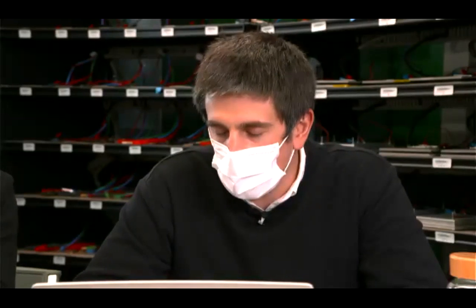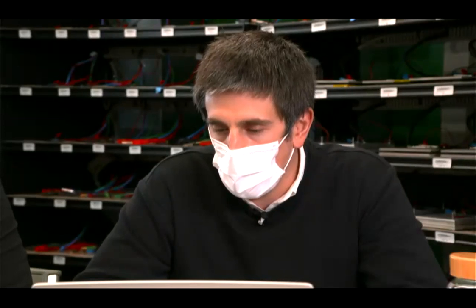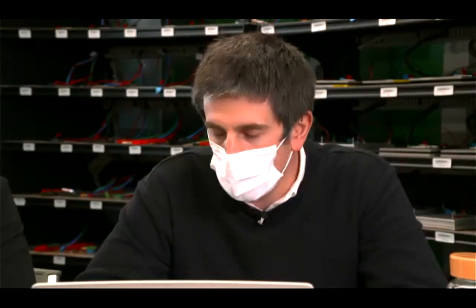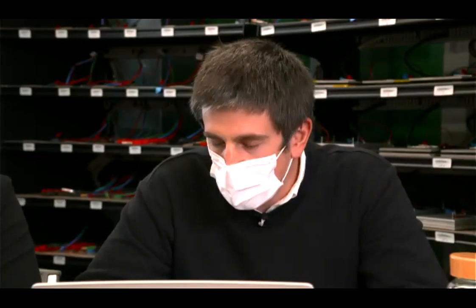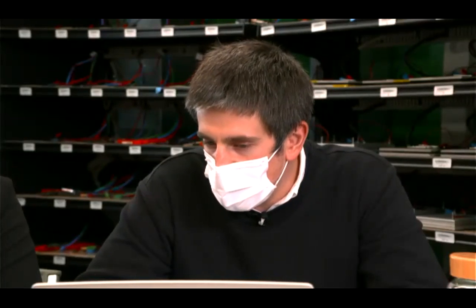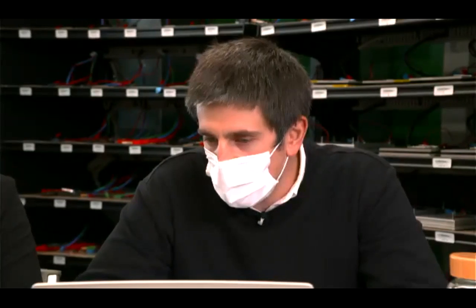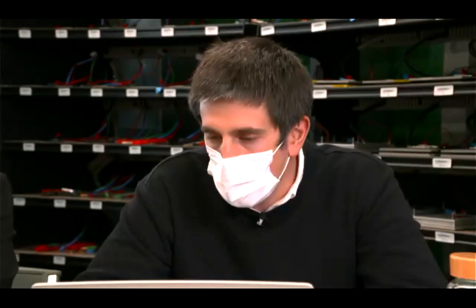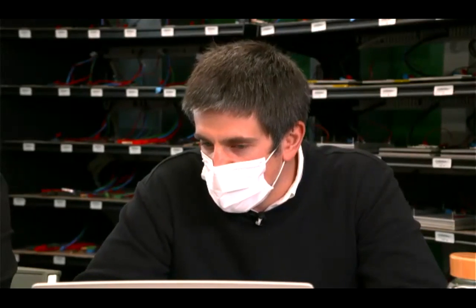Of course, it's not good to have a very low amount of electrolyte because there is some active material that is not working. But it's also true that having a lot of electrolyte is not good either, because the cell is not in a good condition. So we have to do this optimization beforehand with the calculations that we do with the porosities. For every system, because of the layers that we have and the porosity of its electrodes, we have to calculate this for every type of cell. Once we have this, for example if we have to make 50 cells of one batch of this kind of chemistry and electrode design, all of them are going to have the same electrolyte amount.